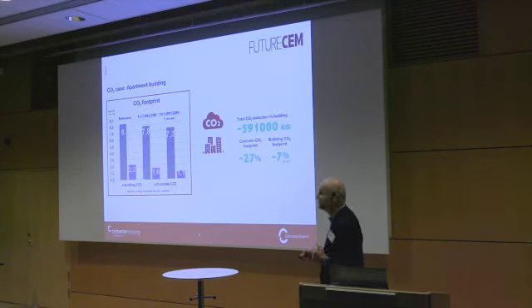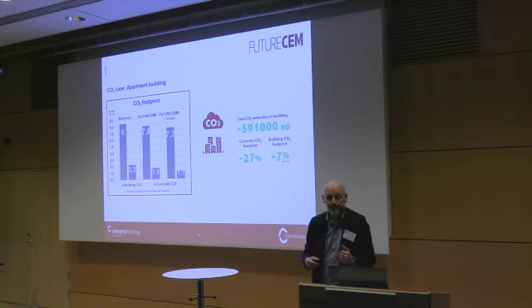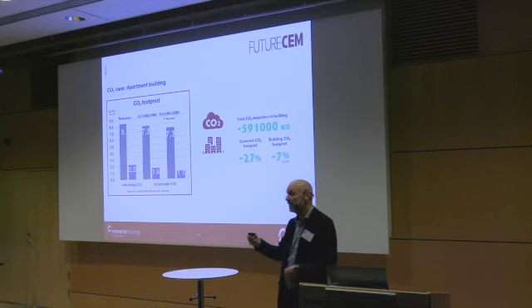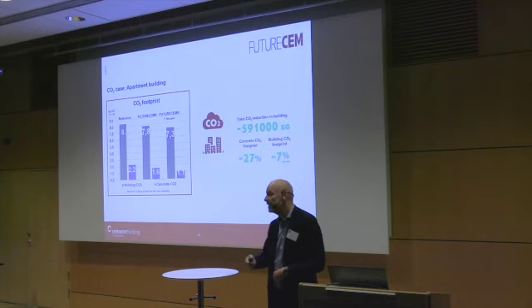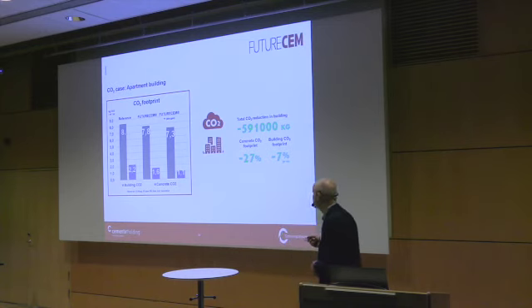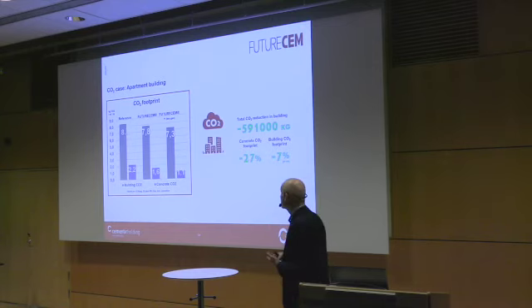We did some calculations on what that would mean in a building, and this is one example from an apartment building. We had a reference. We looked into the FutureCem, but also a FutureCem in the future, where the fuel for the production was switched to biogas, and that means more or less zero CO2. And what we could achieve in the concrete was a 27% CO2 reduction compared to the traditional Danish technology, which would be fly ash and CEM I.